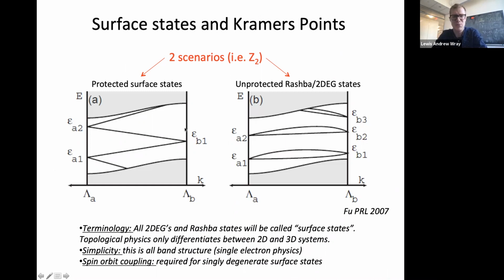In a topological insulator, what you have is states that zigzag their way across the bulk band gap, and that are like a string that connects between the states at the top and the states at the bottom, so that you cannot remove these surface states. If you try to pull them down, you'll just pull more of the string from the state continuum on top. These states also have exotic properties in terms of the spins of the electrons. They constitute a new kind of electron system at the surface of a material.